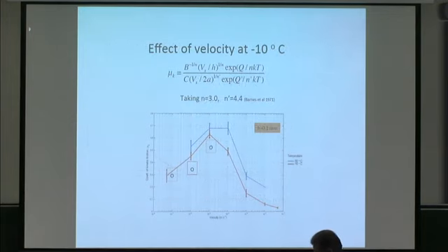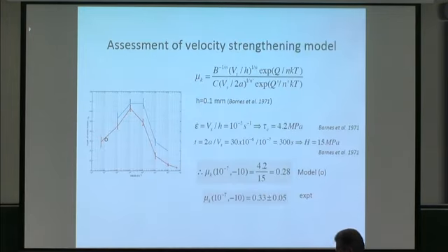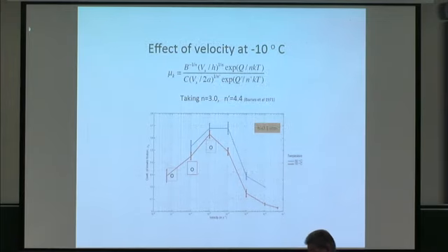If you ask, what about the effect of velocity? Well, here we are. The next two other velocities, higher by each an order of magnitude than the former one. Using that same deformation zone of 100 micrometers, we find that it's not quite good. We're down a bit in the calculation. But I don't know how good is 100 micrometers in terms of the deformation zone. Perhaps 50 micrometers might work.